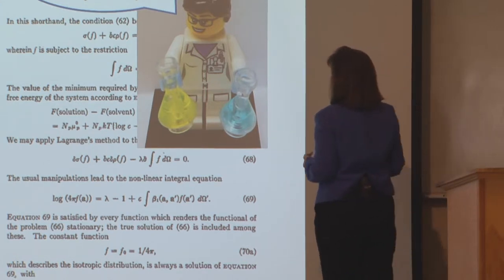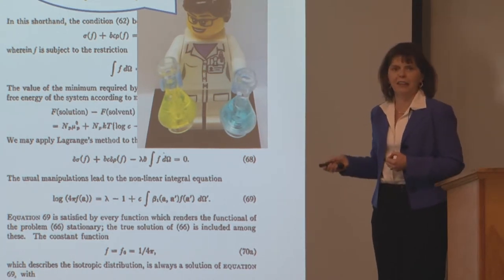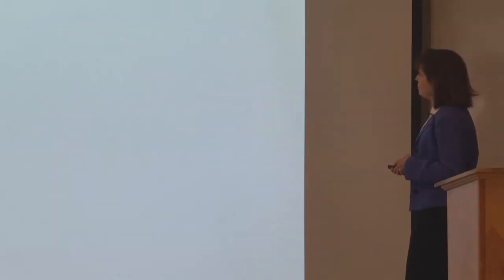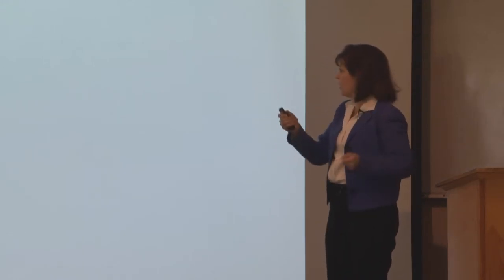The fundamental basis for most of our research comes from a 1949 paper by Onsager. If you have two rods in a solution, they can wander around, rotate and translate, and they'll never interfere until they get more concentrated. Then they won't be able to rotate without hitting each other, but they can still move around a lot. If you imagine them getting more and more concentrated, they'll barely be able to wiggle — like getting on the train in the Atlanta airport at peak time. But at even higher concentration, things have to start aligning, and at higher concentration still, they have to start pointing in the same direction. Thermodynamics doesn't have a time scale, so the time scale might be too slow for an industrial process, but we can help it along.